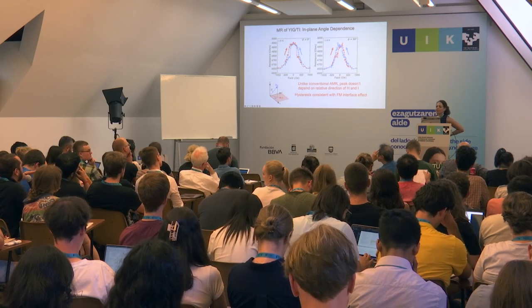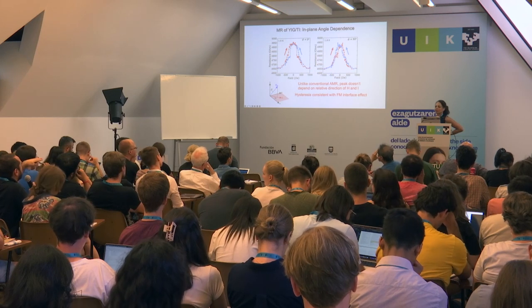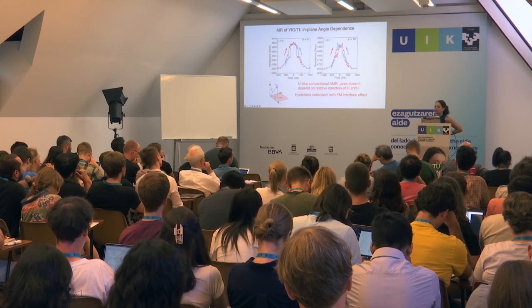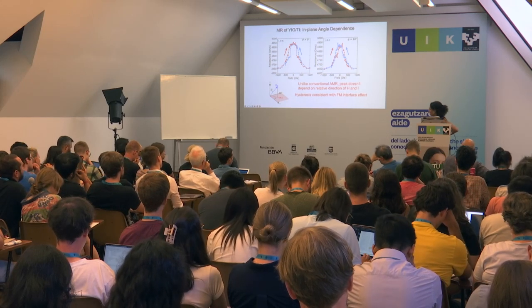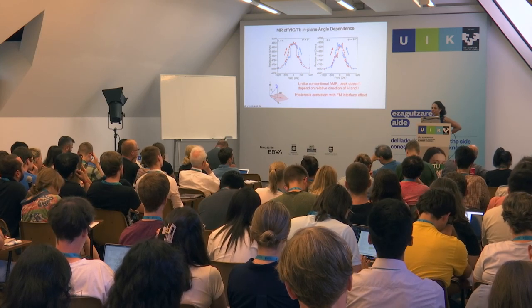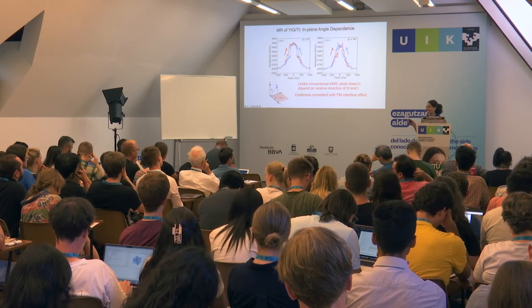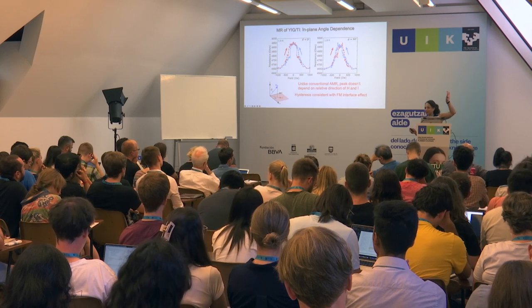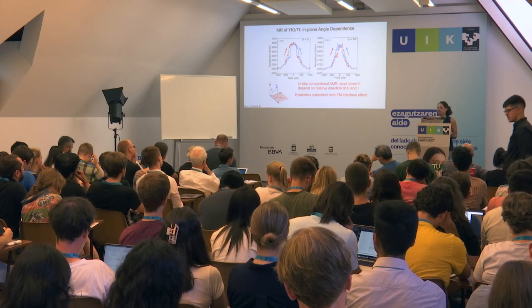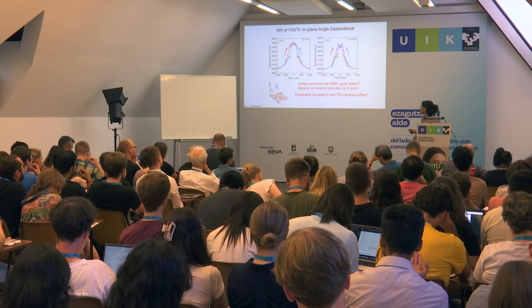And you didn't try to make the same experiment to see the resistance for a flake on top of a non-magnetic insulator, just to see if the YIG is affecting the resistance? We have done many experiments with a flake on top of non-magnetic insulators, and we don't see switching effects or anything like that. But the resistance as a function of temperature, is it the same, or does it change? It depends on the flake. Okay. We sometimes do see the semiconducting behavior, and we sometimes do see the metallic. So that just depends on the flake. But if you take a flake that's not on a magnetic material, we never see this effect. Okay. Thank you.